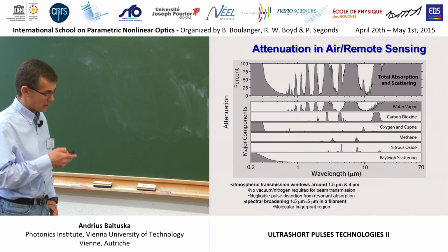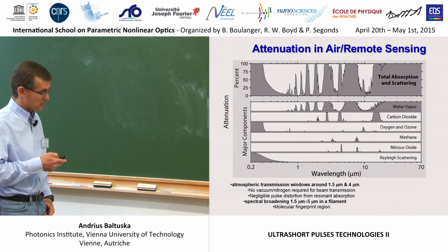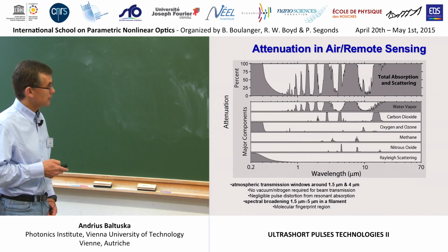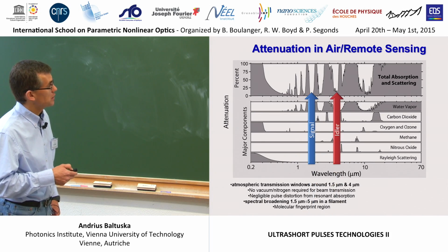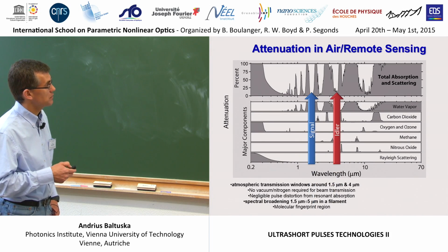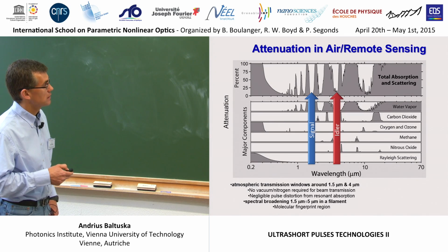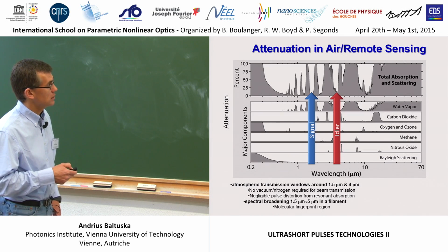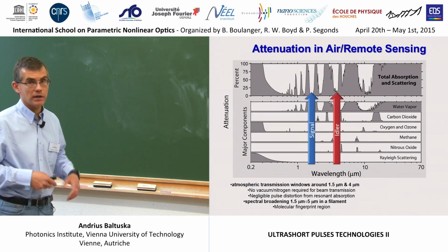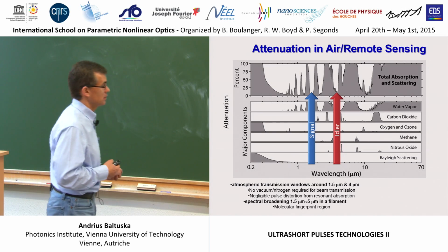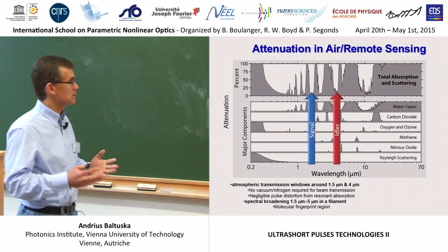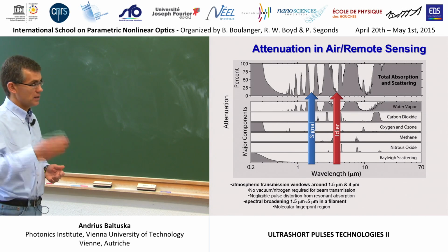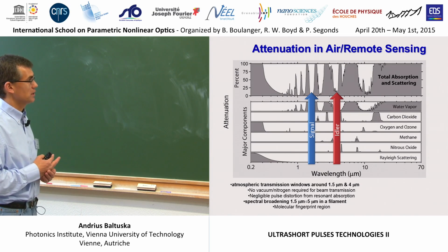If you look at atmospheric transparency, you notice that we're working within 2 transparency windows. One is around 3.5 microns, and it's limited on the long wavelength side by CO2 absorption at 4.2 microns. So this is a good coincidence between what the crystal can support and where air absorption will start to limit you anyway.